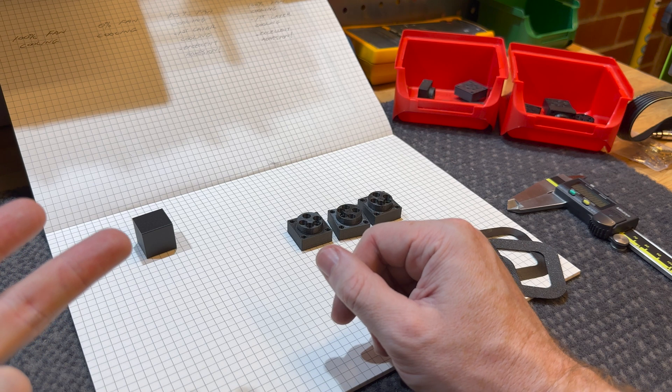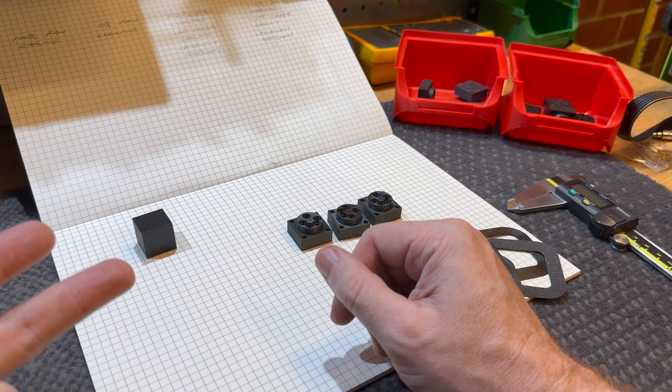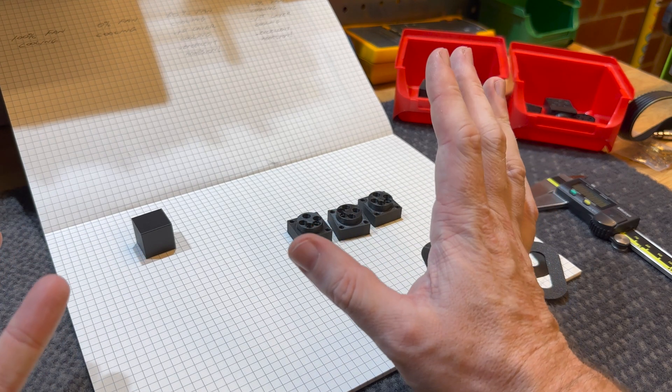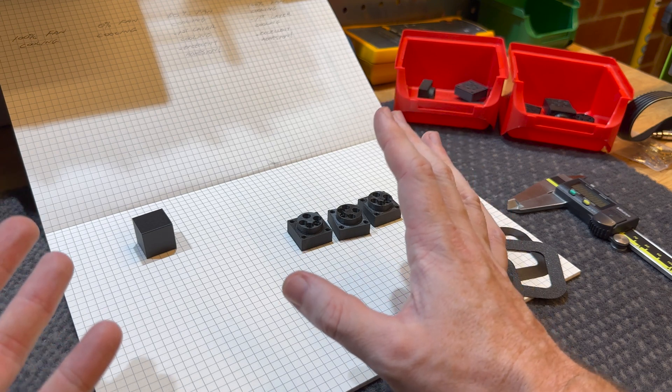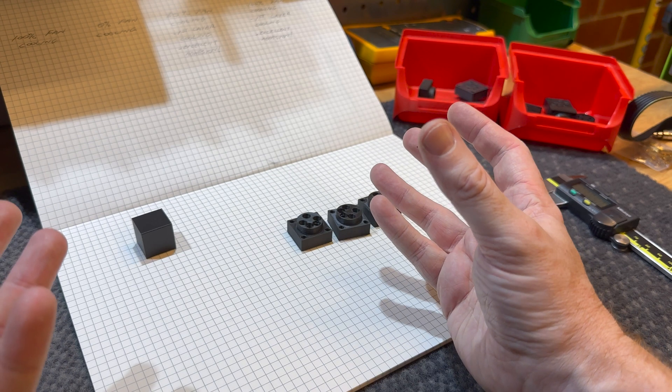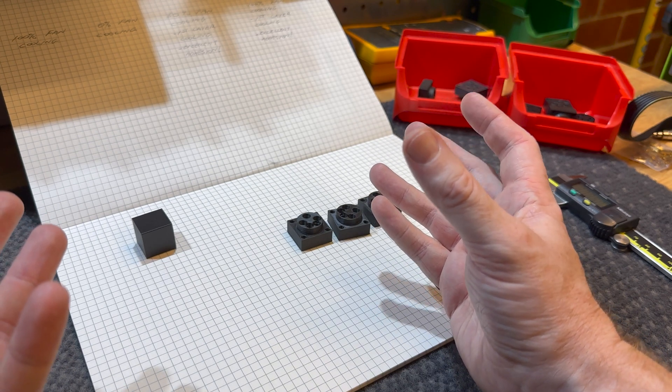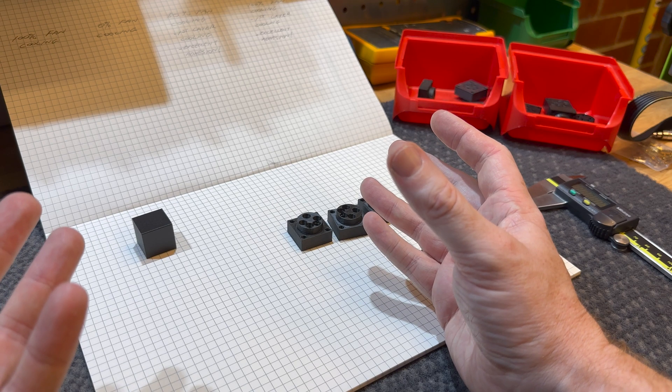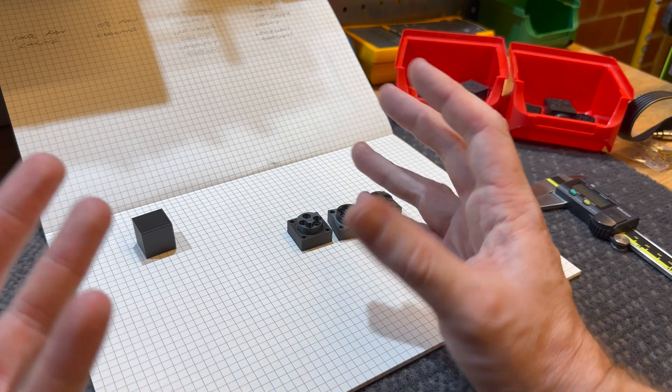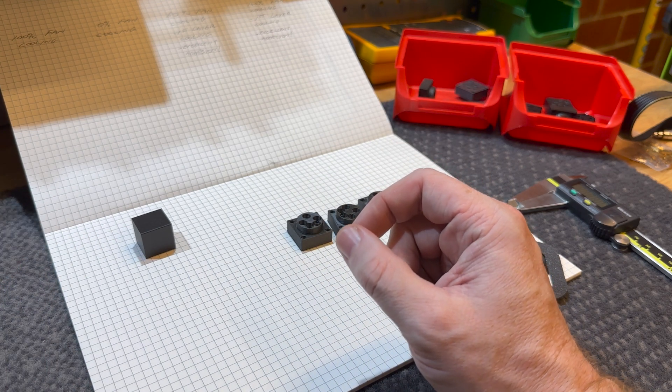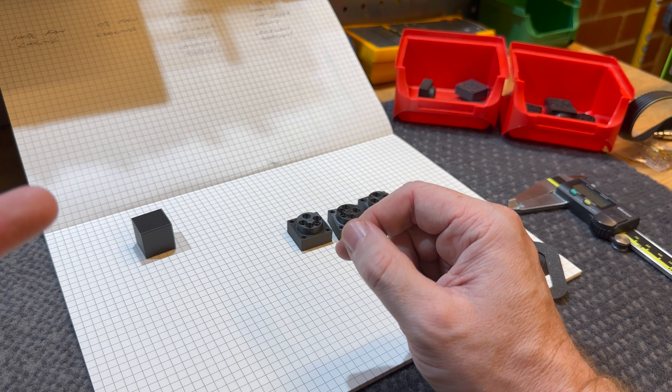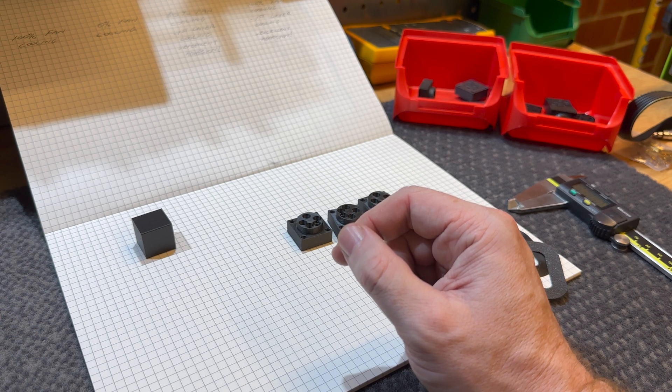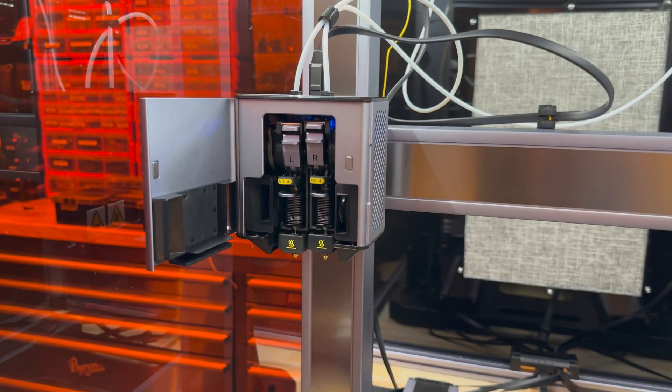The Onyx—either my Bowden tube is a little bit tight or I need to adjust it a little bit, because the Bowden tube was struggling with the Onyx filament. If it sat in there for a few hours, I think it was swelling in the Bowden tube and then it was binding up in there and wasn't feeding very good, and that caused a lot of problems. I found if I was starting it again overnight, you need to purge the line before doing another print or make sure your Bowden tube is really well-worn or it's got enough clearance to feed that Onyx after it swells a little bit.